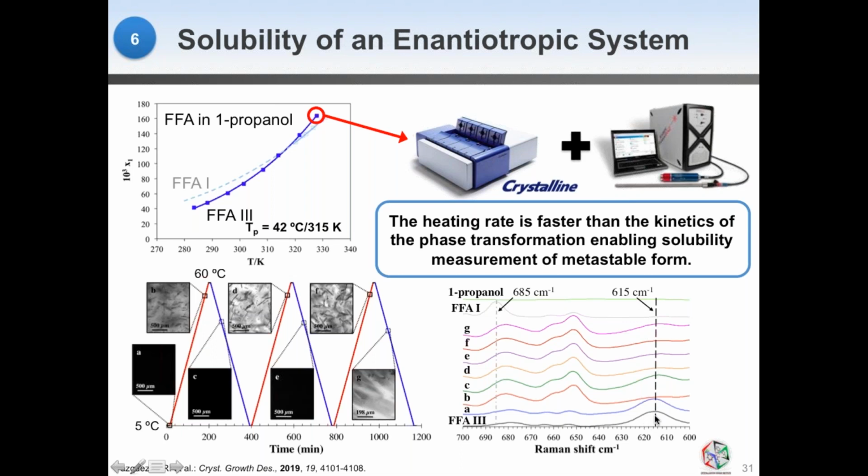And throughout these heating and cooling cycles, we nucleate and maintain in the solubility measurements our peak for form three. So we can really ensure through this in situ measurement that we are able to accurately measure the metastable form. And this is possible because the polythermal method with the relatively fast heating rate with respect to the phase transformation kinetic can actually outrun this transformation of the metastable form to the more stable form, in this case,